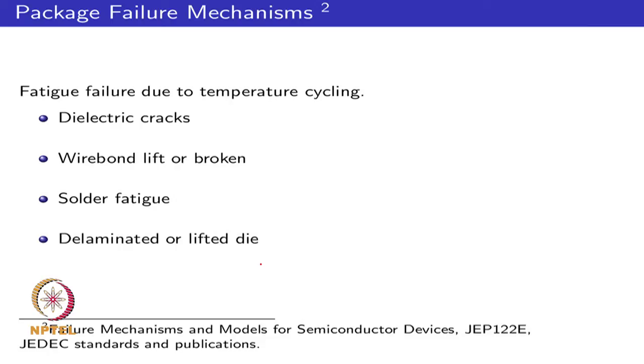After these problems like wire bond liftoff and delaminated corners of the chips, you end up with non-uniform current density within your chip, which can cause even further heating, which can further accelerate the temperature-related degradation within the power module.